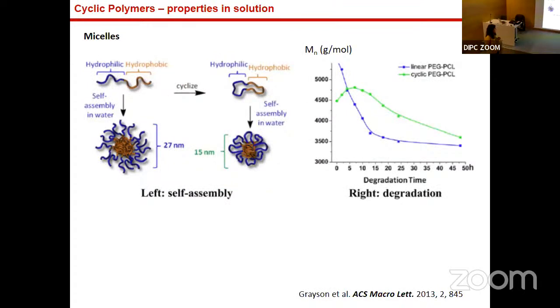Micelles, for example: Scott Grayson synthesized micelles from copolymers with a hydrophilic and a hydrophobic part in the chain. He compared the cyclic polymer with the linear one, and he observed smaller sizes in the cyclic micelles, and also differences in the degradation profile. The degradation profile is the molecular weight, how it is reduced as a function of time. He did an acidic cleavage of the polymer, and he observed that it was retarded in comparison with the linear one. So there are many properties that are related to just this cyclic topology, and that we can use in the future, probably for some applications.